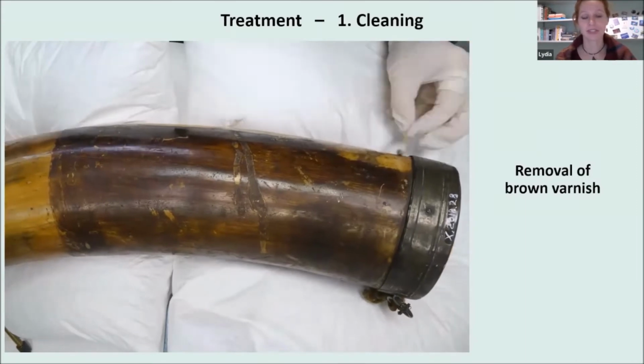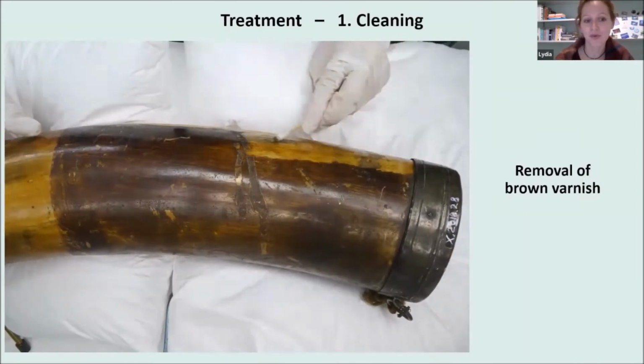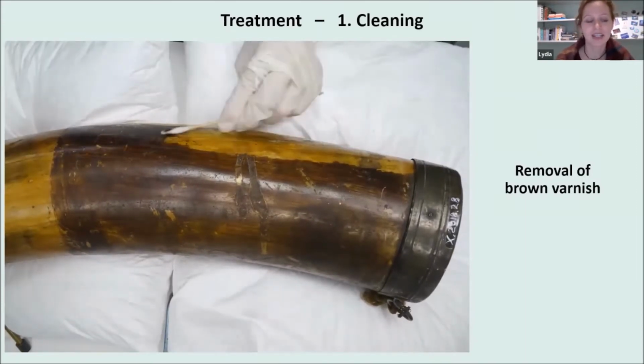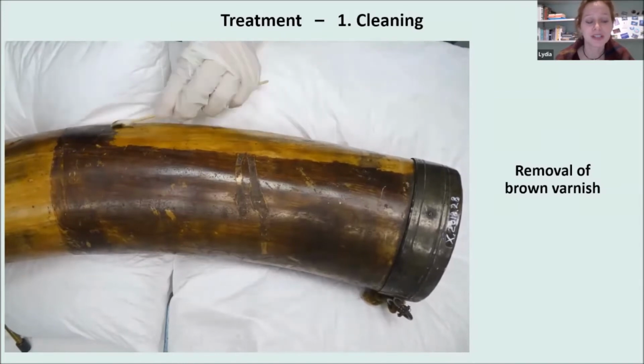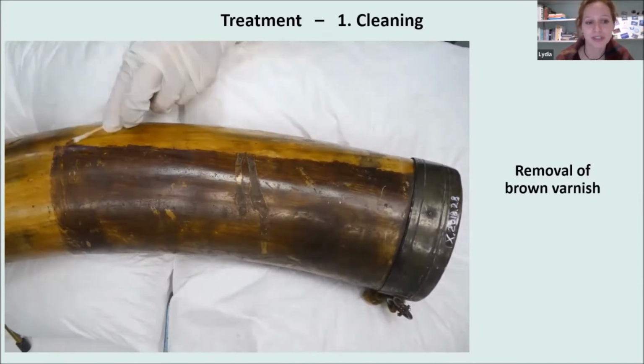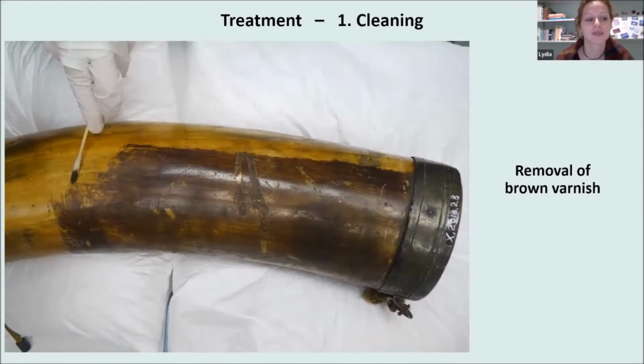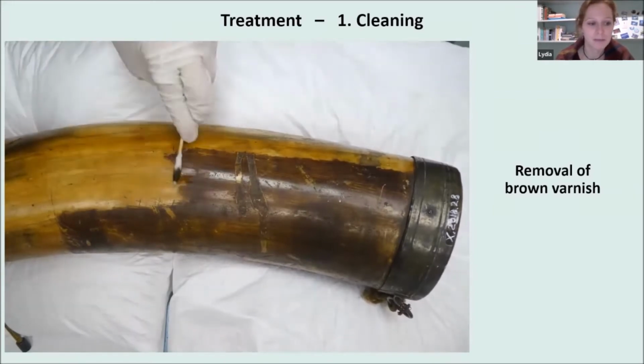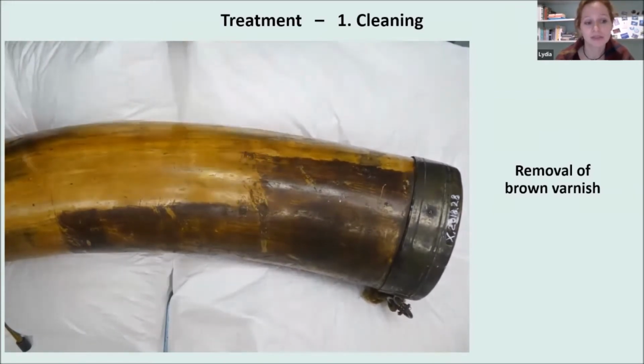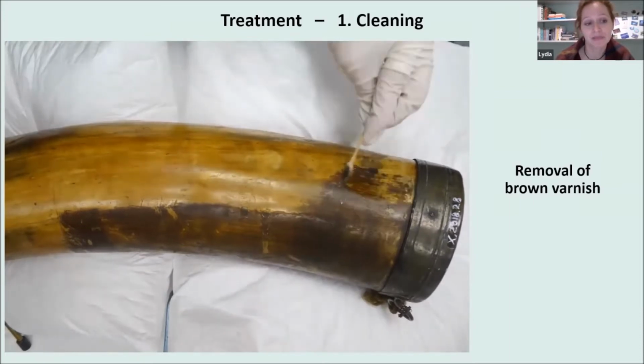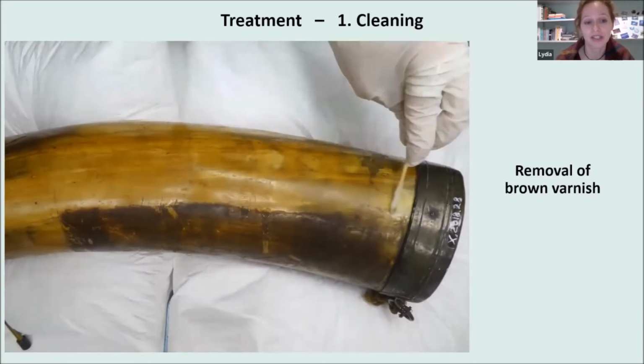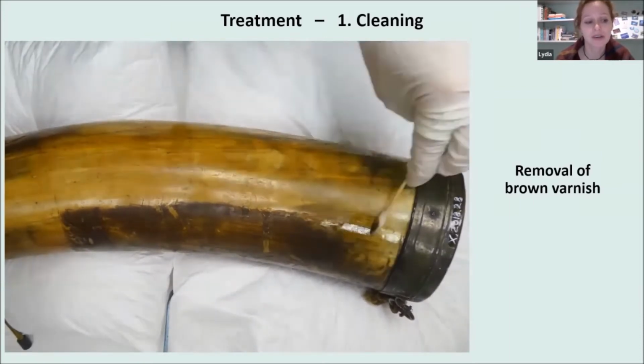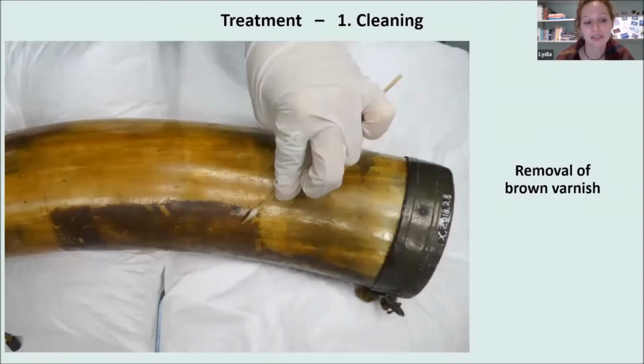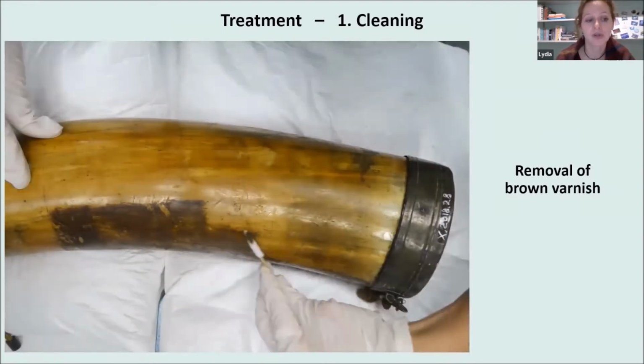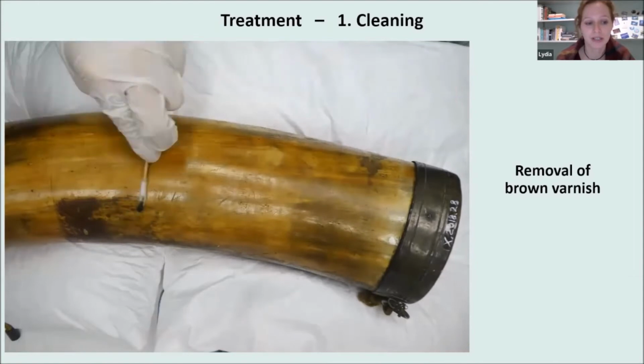I started with the easiest task, the removal of the darkened varnish. I was hoping to remove the varnish with a gentle solvent mixture, as I wanted to avoid that the material will dry out, though only acetone achieved a successful removal of the varnish. Luckily, I found the underlying surface stable and no structural or visual change occurred.